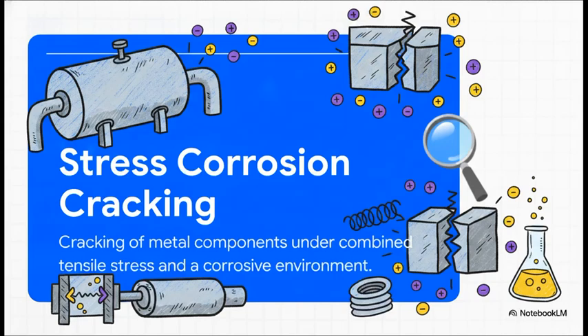So if you've got high levels of aggressive chloride anions or caustic sodium cations in your boiler water, they will literally attack the microscopic grain boundaries of the stressed metal. They essentially unzip the steel and split it wide open.